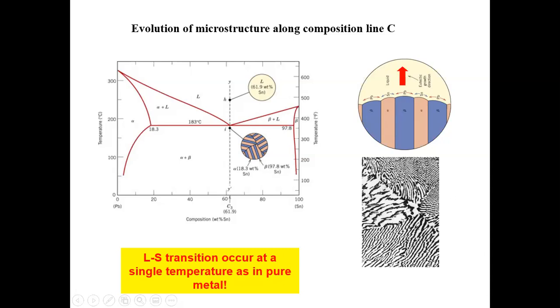Below that is the microscopy image of that kind of structure, right? Yes, this is an image, but I don't know what this image is. Probably it's an optical image. I'm sorry, I didn't show you a bar, but the size of this image is roughly 100 or several hundred microns, probably 100 micron across. So this is a real image of the eutectic structure, and you don't see this ordered way of separating, and you don't see the same spacing across all the sample. It's because you probably have some grain structures underlying the growth of the eutectic, and because you probably have a different temperature, so they have fluctuations. So you don't see the perfect stripe structures, but this is the way how we typically illustrate that.